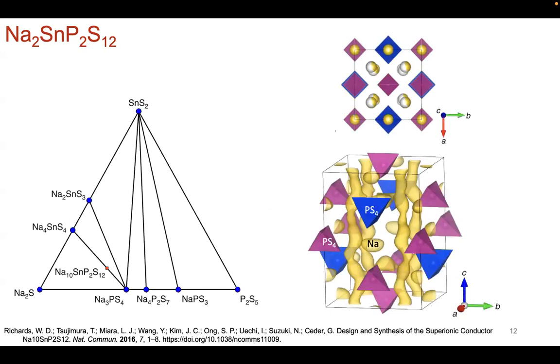Now, you can't talk about phosphate-based solid electrolytes without talking about LGPS, but in terms of the sodium equivalent, we'll focus on Na10SnP2S12, right? So if you look at the ternary phase diagram, you could see that when you combine Na2S and Na4SnS4, stable ternary compounds and Na3PS4, you get this quaternary phase on the tie line. So it's a stable, thermodynamically equilibrium compound that you can access. And so you can see here the channels of sodium ions that can migrate throughout the compound that can make it a fast ion conductor, which is really exciting.